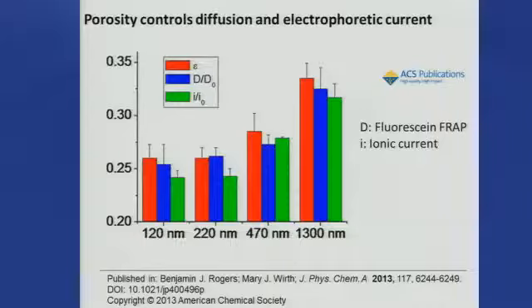And I said that we made the assumption that this ratio of diffusion coefficients was the porosity. We independently measured the porosity. And then, this is actually from the 19th century, James Maxwell said that the porosity should be measured by the ratio of the current in the material to the current without the material. And what we found was all of these things agreed. So as far as I know, we're the first group that actually measured both diffusion coefficient ratio and current ratio and showed that they agreed.